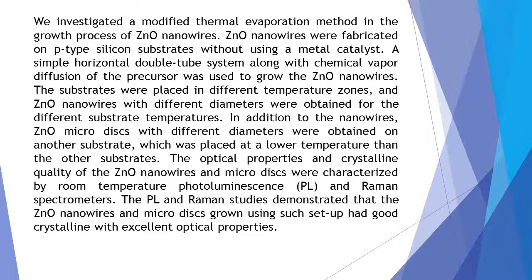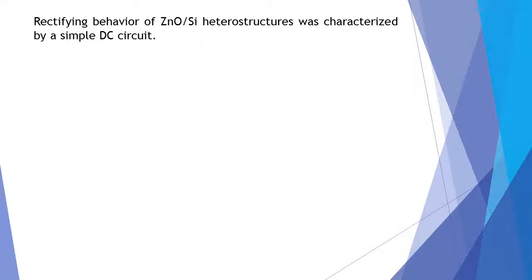The PL and Raman studies demonstrated that the ZnO nanowires and microdiscs grown using such a setup had good crystalline quality with excellent optical properties. Rectifying behavior of ZnO/Si heterostructures was characterized by a simple DC circuit.